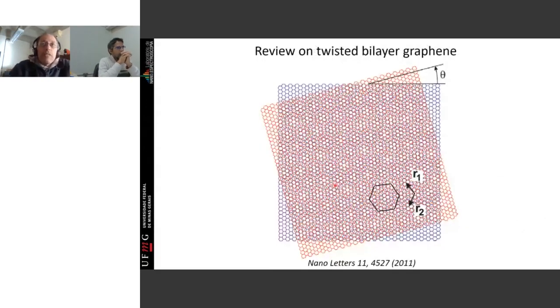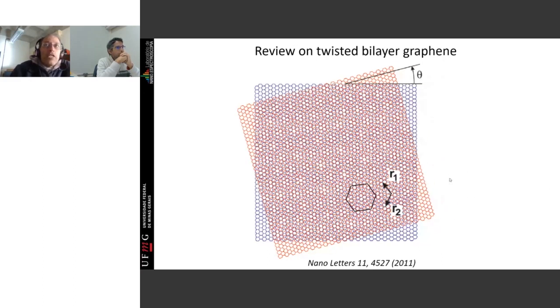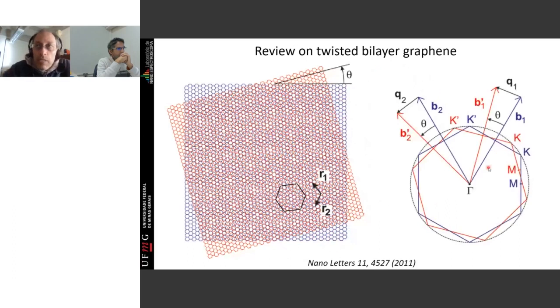So here is a twisted bilayer graphene. This is the name, or this is the twisted bilayer graphene. Here is the superstructure that repeats itself because you have the hexagonal periodicity in this twisted system. And this enlarged unit cell in the real space generates a change in the so-called Brillouin zone or reciprocal space. The real space is where the atoms are. The reciprocal space is where the waves, like vibrational modes or electronic waves, live.